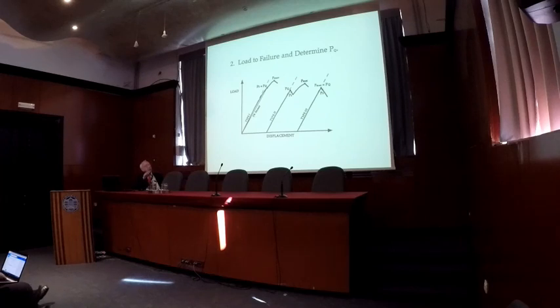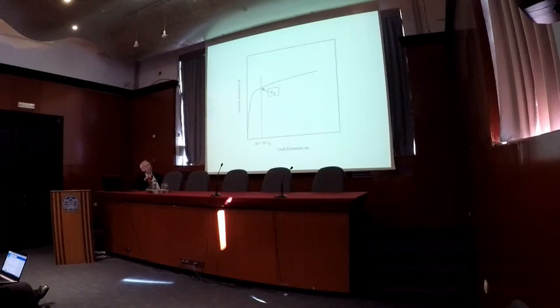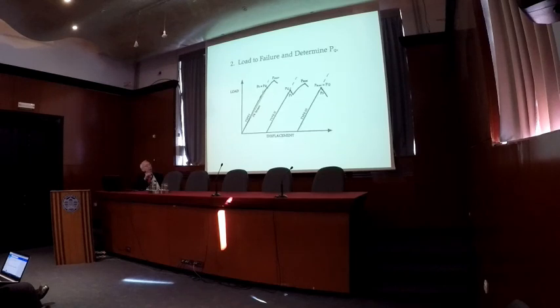Now the PQ is the maximum load you encounter up into the crossing of the 5% secant. And what that does is give you a point on the R curve that is at 2% of the initial crack length. So picking a point on the R curve is actually done by doing this secant analysis. And that works for many materials that have ductile fracture. For brittle fracture, you don't have to worry about that. You get a well-defined point. So this third curve would be brittle fracture.